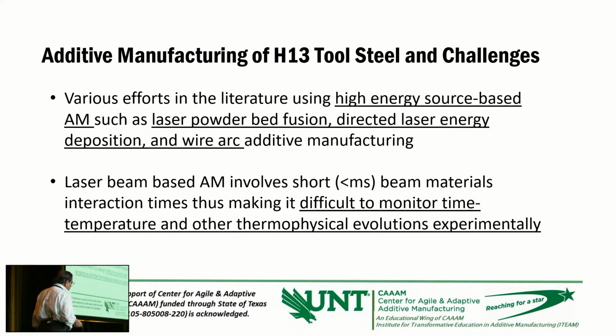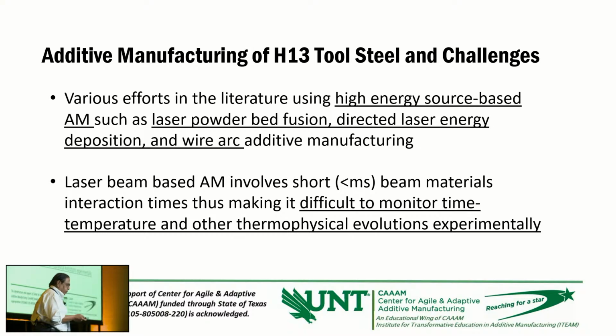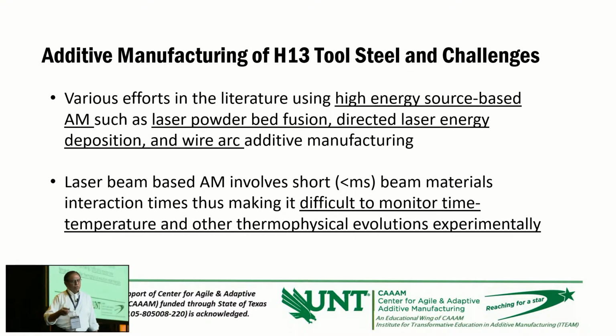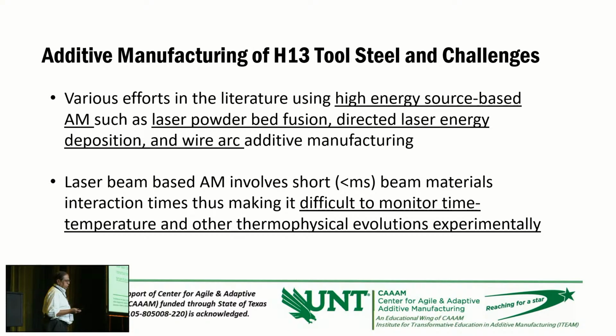And what happens is the time is very short, the interaction zone is very small, because the laser beam typically used in this additive manufacturing process is a few microns in diameter. So the time is short, as well as the interaction zone is very small. So monitoring this process is very difficult. If you want to do any in situ diagnostic to see what is going on in the region of the laser material interaction, such as measuring temperature or looking at the fluid flow characteristics in the laser material interaction zone, it is very difficult. That is because of too short a time and too small a zone, and there are not many in situ tools which can respond to this kind of extreme conditions.